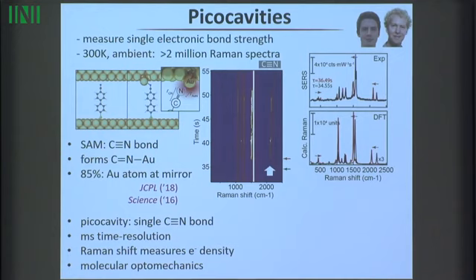And we can do DFT calculations, the black curve here, and it basically fits. We do a good job there. So indeed it works that we can actually shine light against this molecule and see the bonds. We're only looking at about 50 molecules in this gap here, all at the same time, but you can see they're all identical. Except at some point in time, something happens.